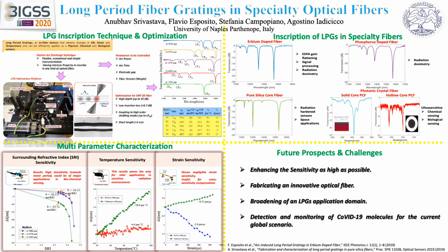Some fibers exhibit extreme or specially tailored parameters, such as an unusually large fiber core diameter or a very high numerical aperture. Also, there are LMA fibers, I mean large mode area fibers, exhibiting particularly large fiber modes. We can also have a fiber where the waveguide function is not obtained simply with a somewhat increased refractive index in the core, like step index fiber, but in some other complex way. For example, we know photonic crystal fibers, which have periodically arranged holes and are also called holey fibers, with quite complex propagation characteristics and structure. Another is polarization maintaining fibers, which have different designs that can be used to maintain linear polarization state over arbitrarily long propagation distances.